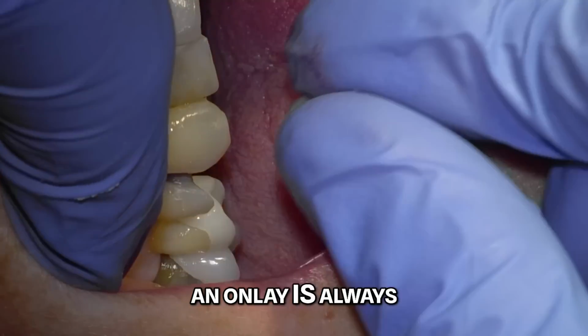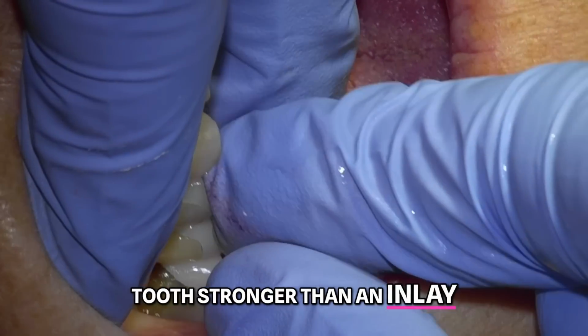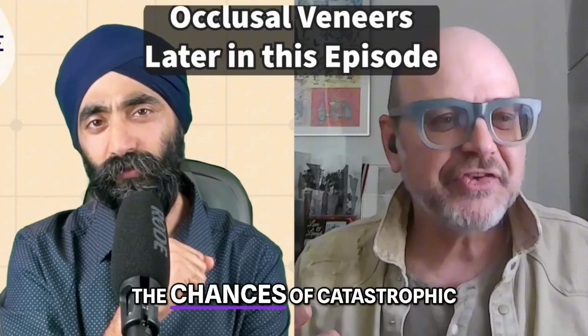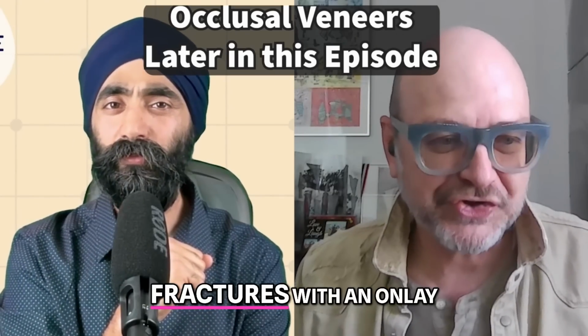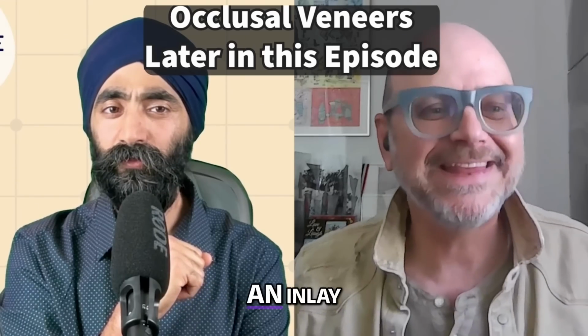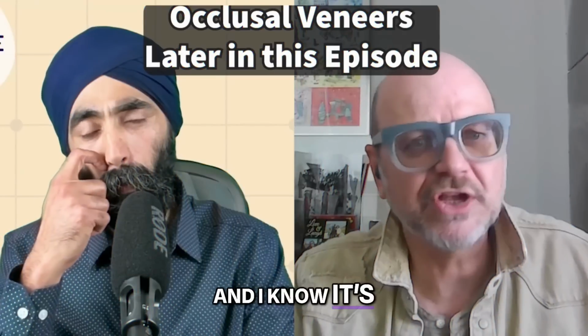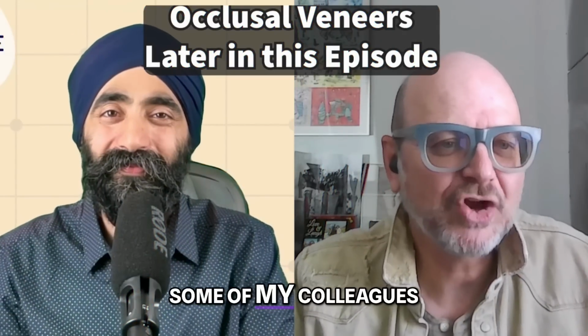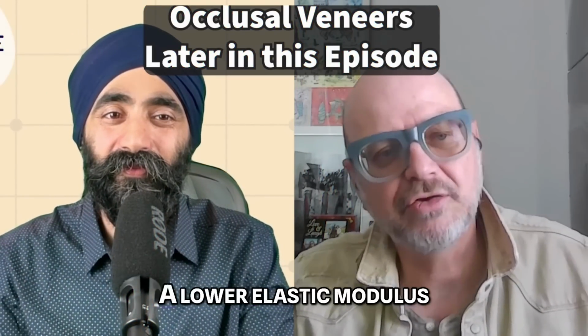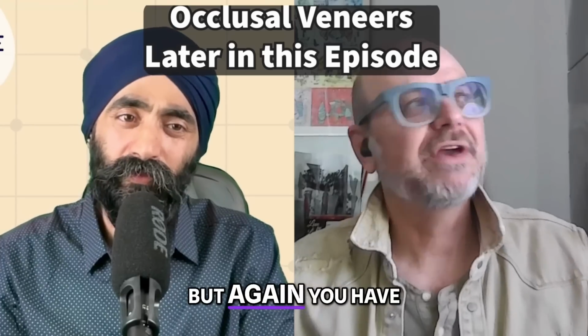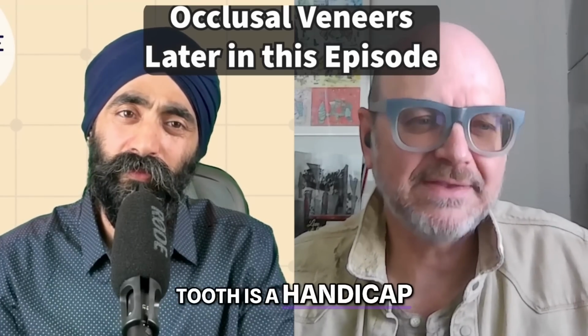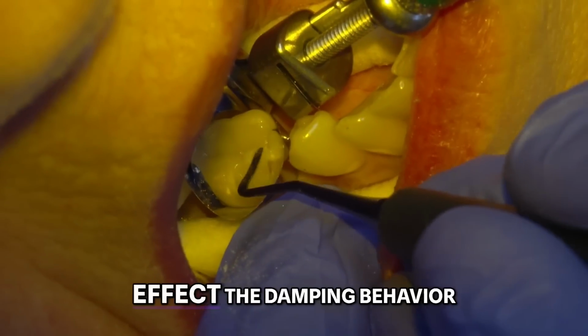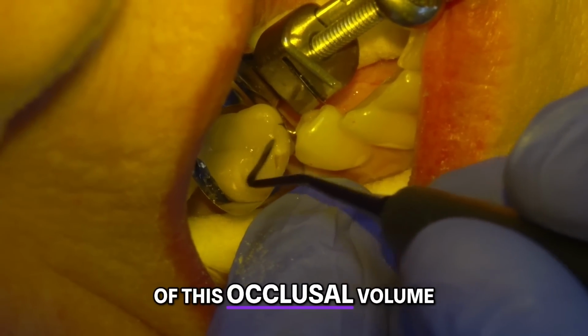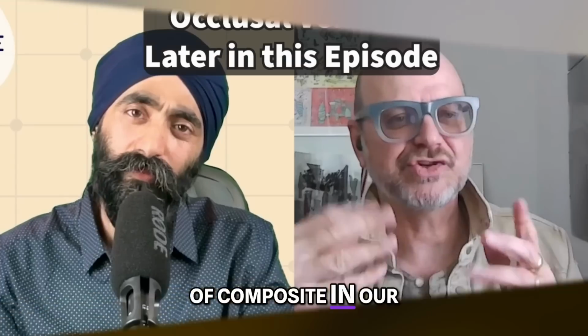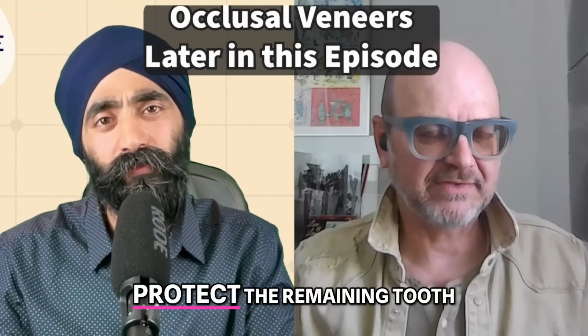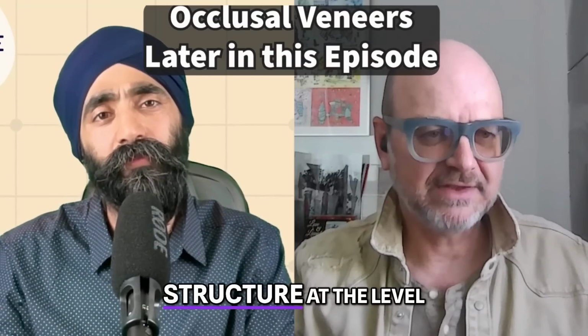An onlay is always going to make the tooth stronger than an inlay. However, the chances of catastrophic fractures with an onlay are bigger than with an inlay, and I know it's not unanimous. Some of my colleagues don't like the fact the composite has a lower elastic modulus, but again, you have to understand a non-vital tooth is a handicapped tooth. So the damping effect, the damping behavior of this occlusal volume of composite, in our studies actually proved to protect the remaining tooth structure at the level of the root.